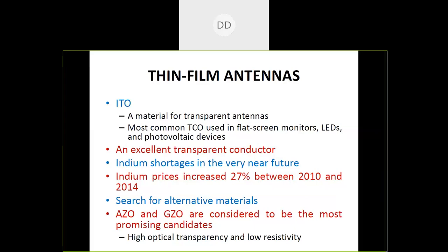But there is an expected shortage of indium in the very near future. If we go through the studies, there was around a 27% increase in the price of indium between 2010 and 2014. So there is a search going on for alternative materials which can be used in place of indium. AZO, aluminum doped zinc oxide, and gallium doped zinc oxide are considered the most promising candidates. These also have high optical transparency and low resistivity, comparable to ITO.